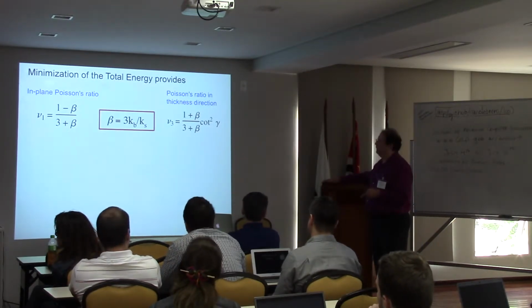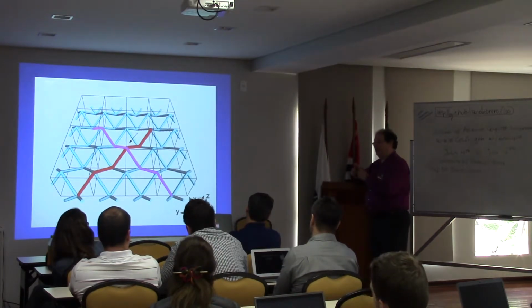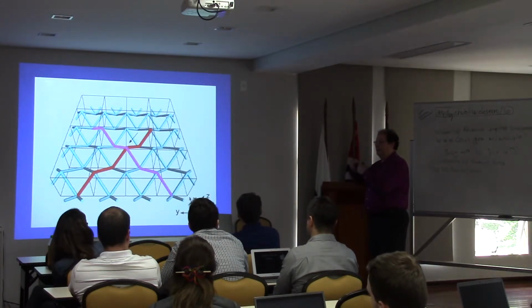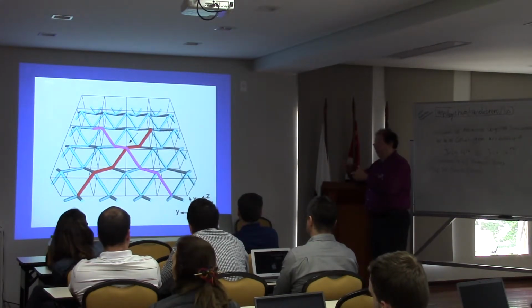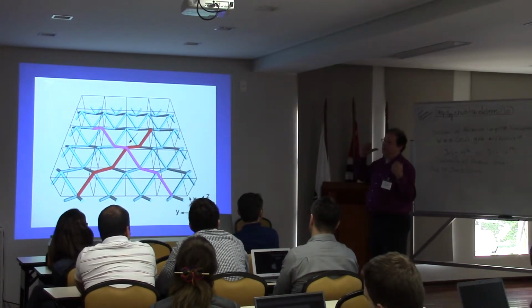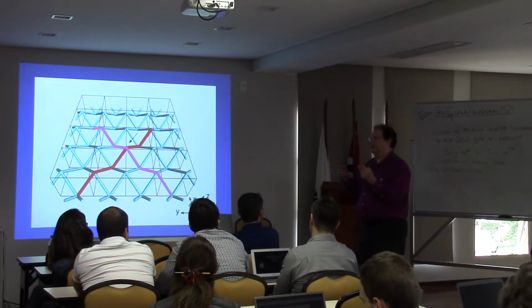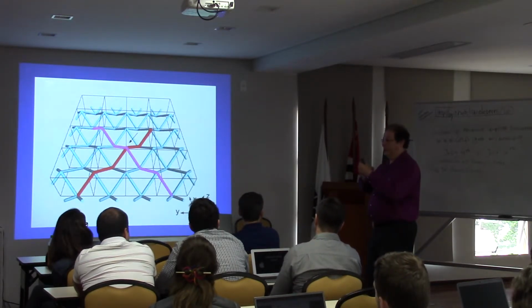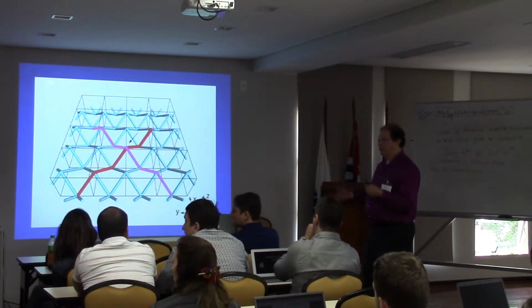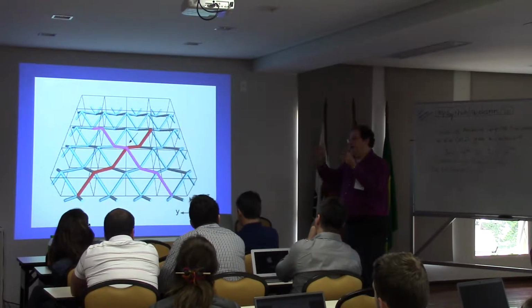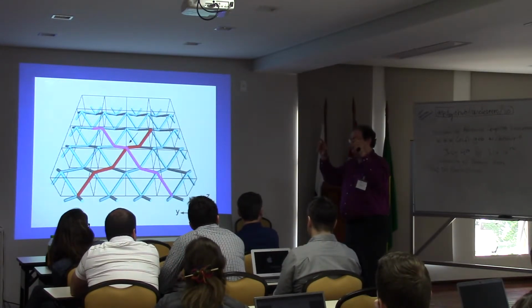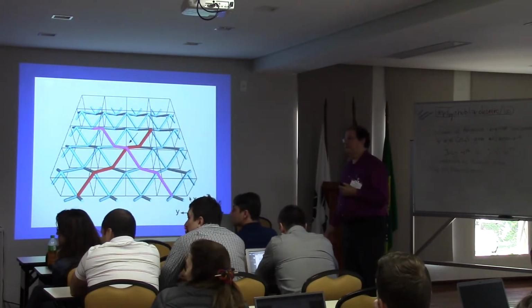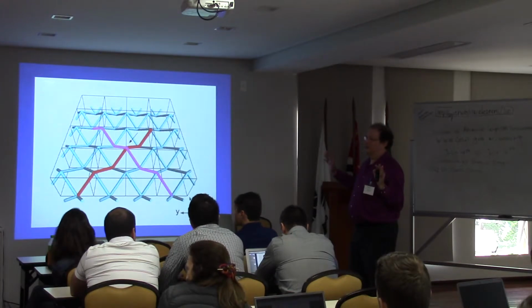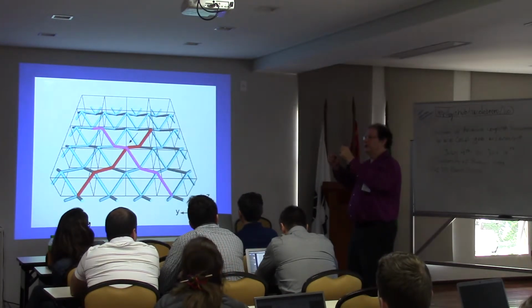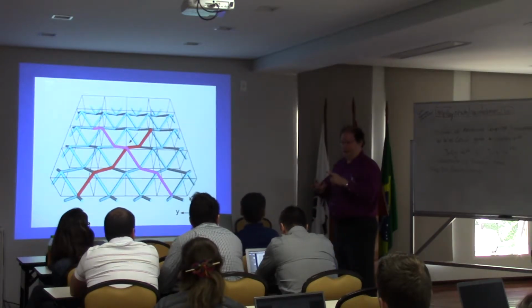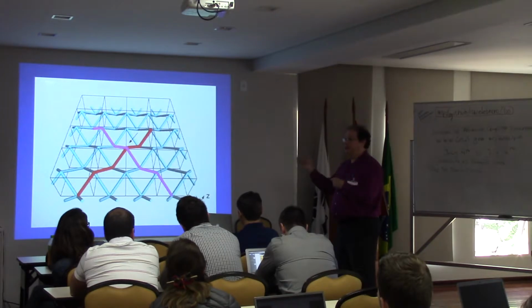What is the model? The model is composed of segments that are free to stretch and to bend. These segments are not atomistic or anything, just segments. We estimate the constants from the atomistic simulation: what should be the constant for bending, and the constant for the stretching that could produce auxetic behavior. So we create artificial segments, small artificial atoms, run molecular dynamics simulation of artificial segments, and we play with the numbers. The material is an ideal material, not a real one. We create new atoms, create segments with these atoms, and then play with the constants in the force field for the stretching, for the bonding, for the inversion, that could produce the auxetic behavior.